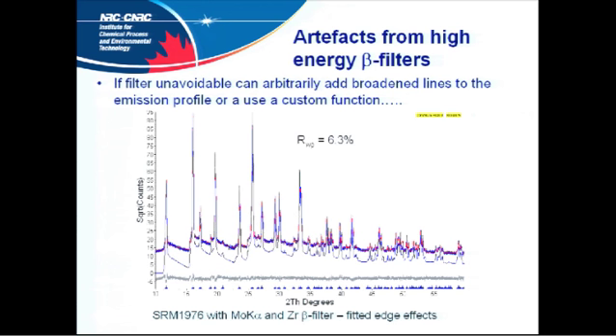If you can't do that, you can start playing around a little bit in your refinement with your emission profile. Now, you can do that on a very empirical basis. This is using Topas, so it's a little bit easier to do this. I'm sure a lot of the other software you could play around with this a little bit as well. Or you can use a custom function, which unfortunately isn't available in the current version of Topas, but will be in the next version. So you can do quite a respectable job of fitting these. The peaks still look pretty ugly, but you can get a reasonable fit.